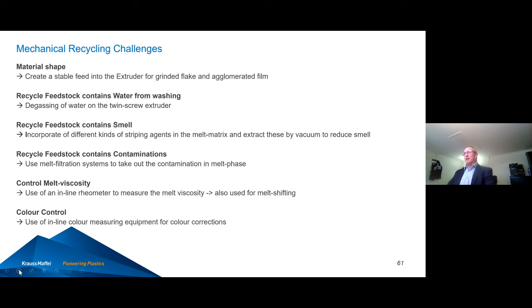Recycled feedstock contains water from washing. The pre-washing being hot wash or cold wash, there's always a big difference in both technologies. What means that the water stream coming with the flake or with the film needs to be taken out of the process, and we do that with degassing steps on the extruder. The recycled feedstock contains smell. Everybody is talking about smell. We have a nice approach.